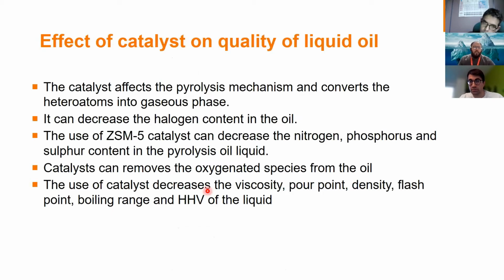What is the effect of the catalyst on the quality of the liquid oil? Basically, the catalyst affects the pyrolysis mechanism and then converts, for instance, if there are heteroatoms like oxygen and nitrogen, into the gaseous phase. It can decrease the halogen content in the oil. So if you have, for instance, chlorine in the feedstock and you're using a suitable catalyst, you can capture a lot of chlorine in the catalyst, and then your pyrolysis oil is free of halogens.